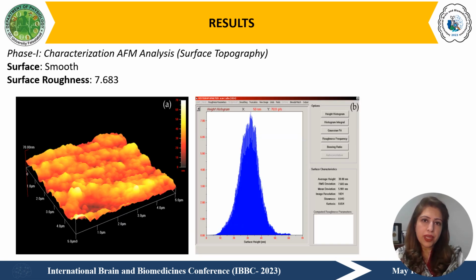Atomic force microscopic analysis was carried out to ascertain the surface topography. The surface topography of titanium oxide nanoparticles synthesized by the jasmine flower extract displayed a smooth surface having the minimal surface roughness of about 7.68 nanometer in size.